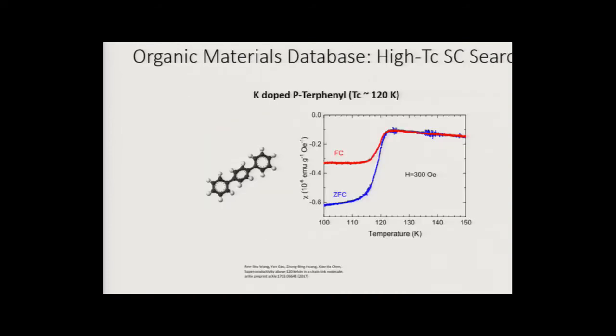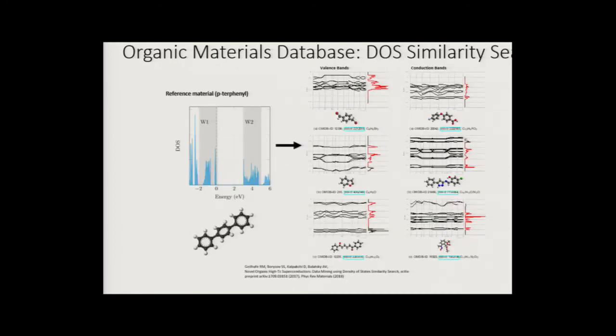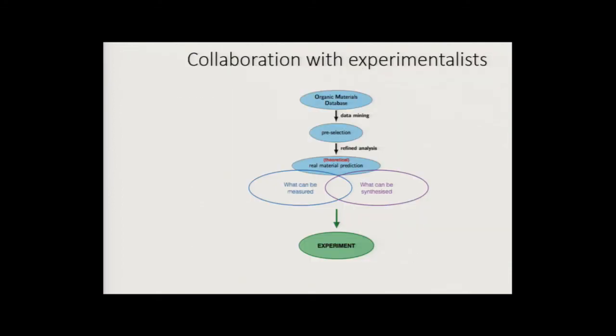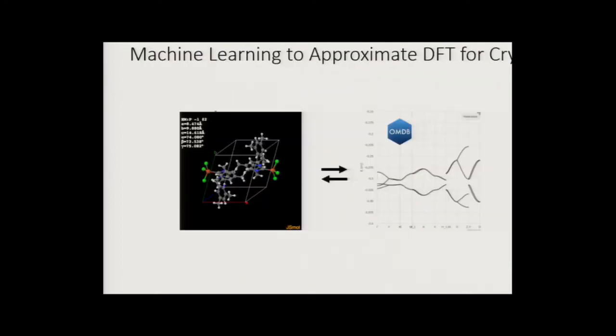And then I would just say that we also looked at a similarity search, motivated by the claim of high temperature superconductivity in organic material like p-terphenyl. We looked for similar density of states for the background compound on which you want to do the potassium doping and presumably induce superconductivity. We find about 15 other compounds which have a band structure very similar to p-terphenyl. So we hope this opens up the search space to find other compounds which might host superconductivity. All right.